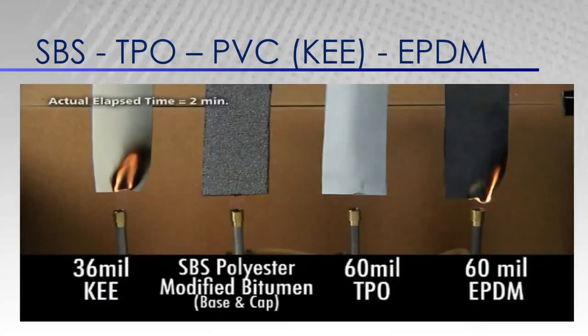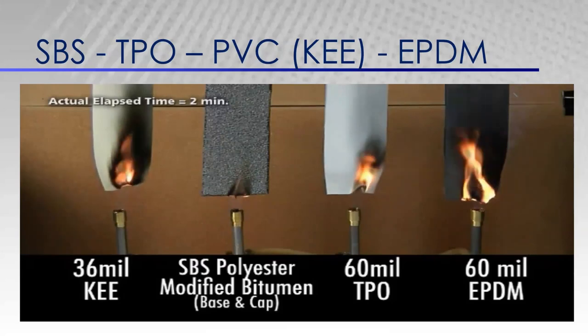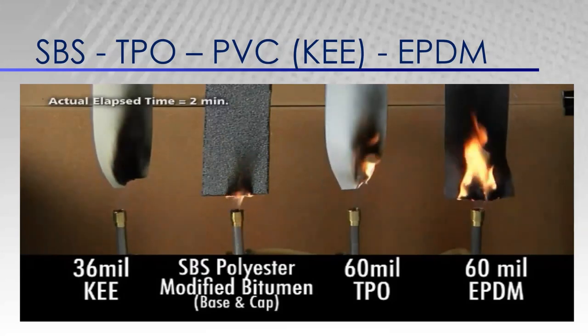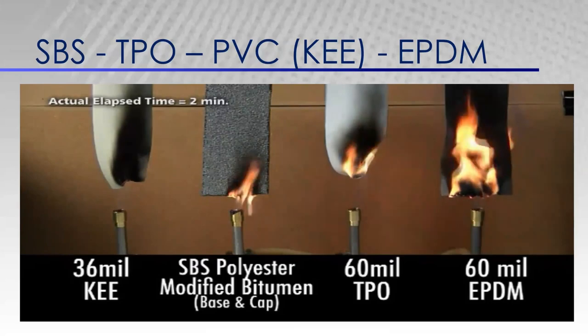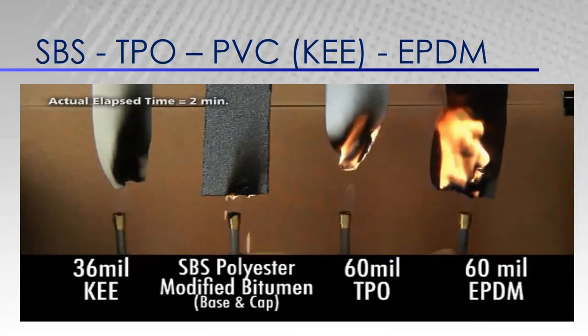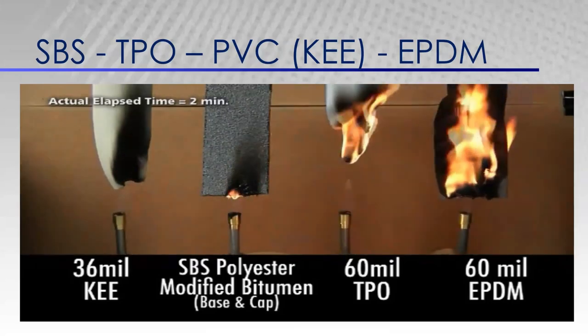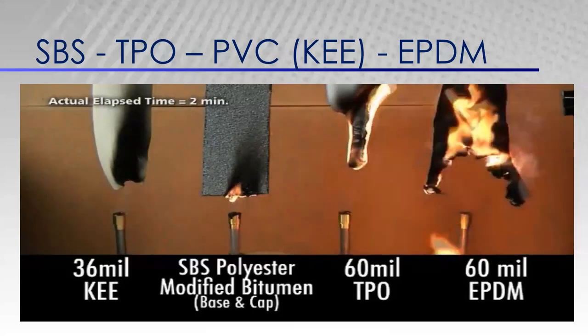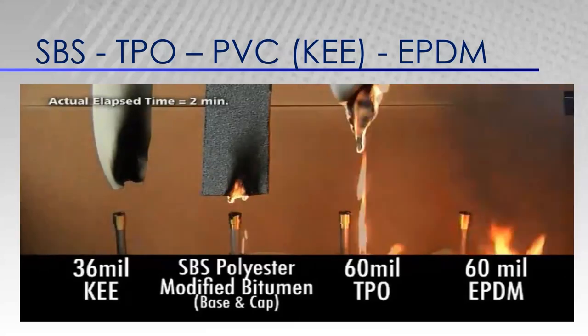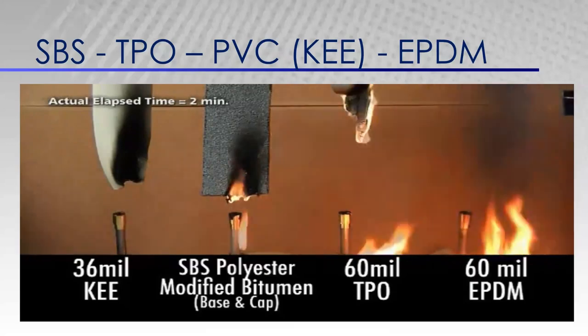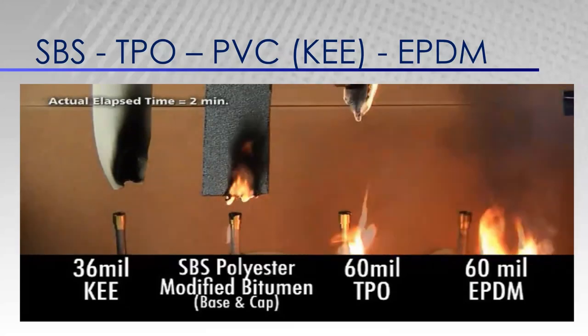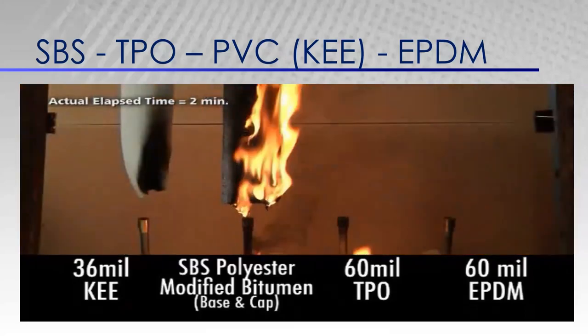These KEE, modified bitumen, TPO, and EPDM samples have been ignited with a flame source. And what you will see is what happens to these products once that flame source is removed. You can see that the KEE has kind of stifled the spread of that flame. The flame has been removed, the SBS continues to burn, so does the EPDM and TPO, just to show you the volatility under flame of those products.